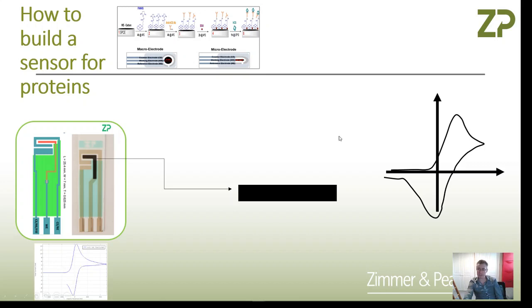So we take the electrode, we characterize it by cyclic voltammetry, and now we have to basically add a coupling agent to the electrode. The coupling agent we use here has kind of two ends to the molecule. One end of the molecule is pyrene. Pyrene is basically four aromatic rings that bind really strongly to carbon. So in this particular example, we're using a carbon electrode, we use pyrene.